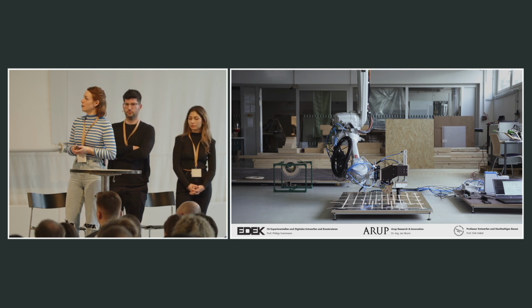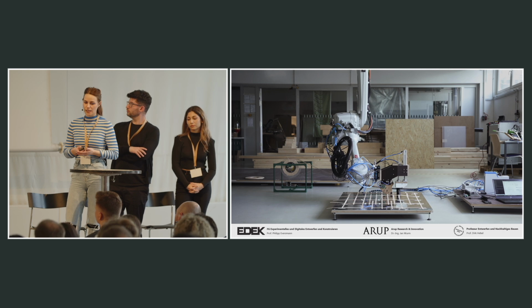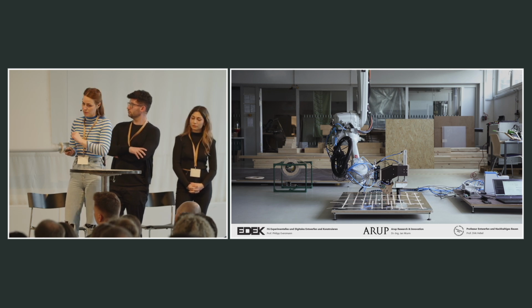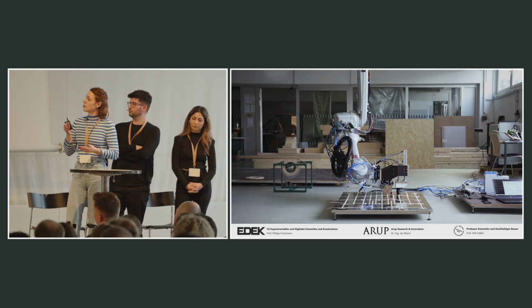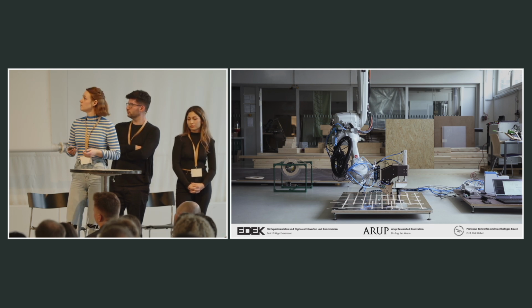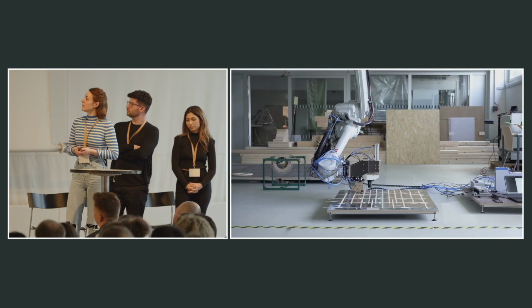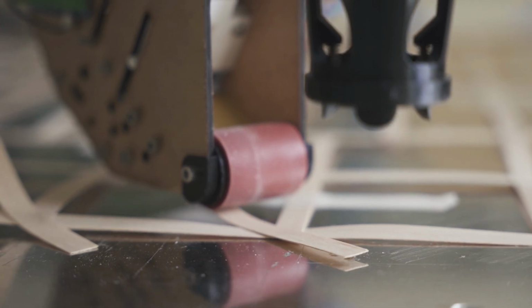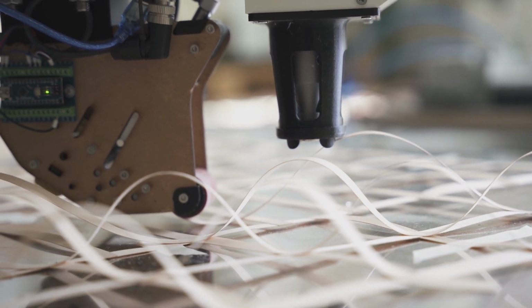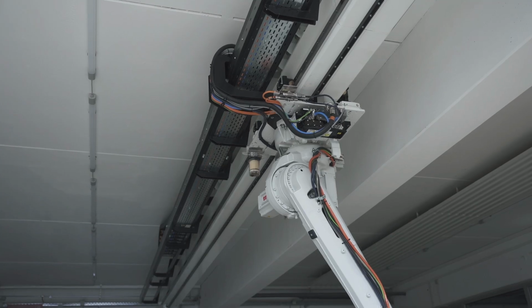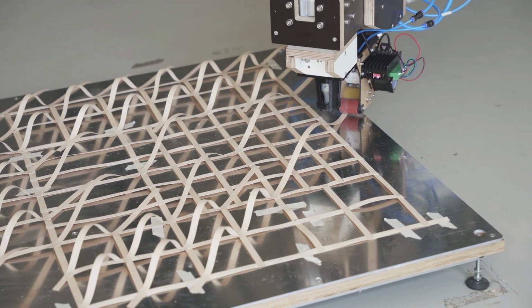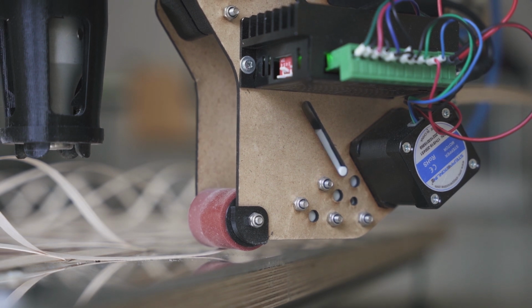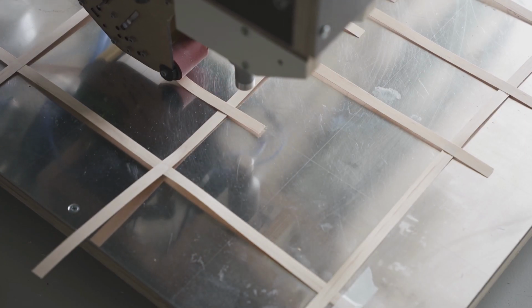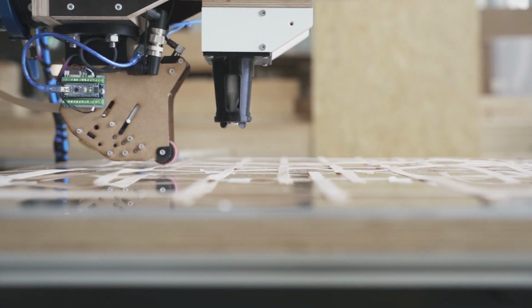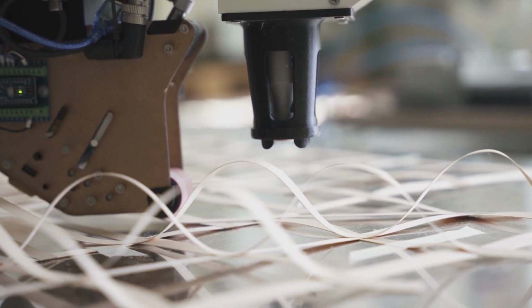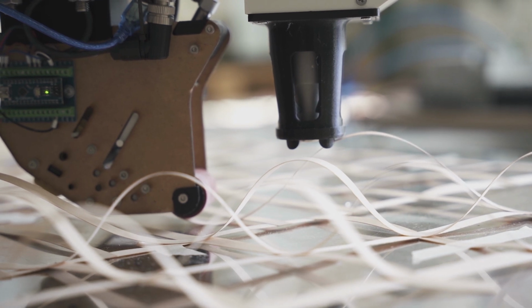So our process is relying on a 6-axis robot and a custom-made end effector, which allows the extrusion of the veneer strips in selected locations, cut them and bind them together to already placed strips. The lattices were manufactured from thin edge-bending rolls of maple wood veneer, which introduce the long fibers into the composite that can be oriented according to the stresses in the geometry. The long fibers act as a reinforcement such as they do in traditional high-performance composites such as steel-reinforced concrete, and also they perform as a natural scaffolding for the mycelium growth.